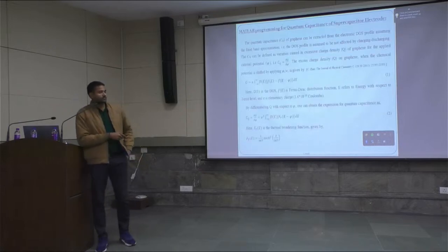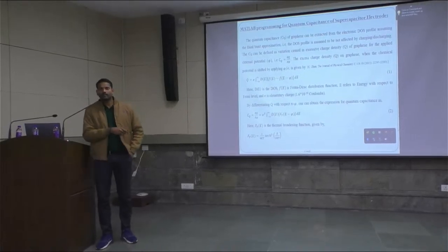Coming to the calculation mechanism, quantum capacitance can be calculated using a few mathematical expressions. First, we need the density of states data, which can be extracted using density functional theory tools. After extracting the density of states data, we have to do some MATLAB programming, or we can use any other programming, such as C programming or MATLAB. And here I have used MATLAB programming.